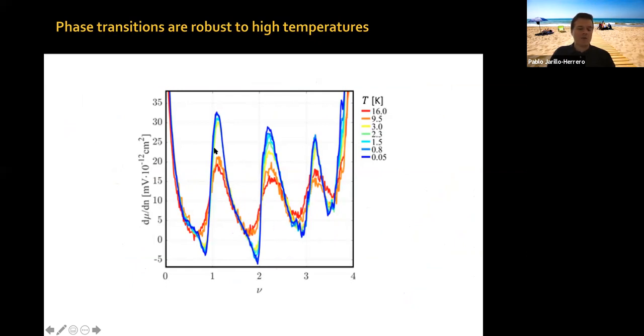In fact, we now have evidence that they persist all the way to 40, 50 Kelvin, something like that. So this is something that is happening at temperatures well above the superconducting temperatures, well above the correlated insulator temperatures. It's a high temperature phenomenon, but of course this has deep consequences for framing what is happening at those temperatures. Okay, so how do we interpret these peaks?